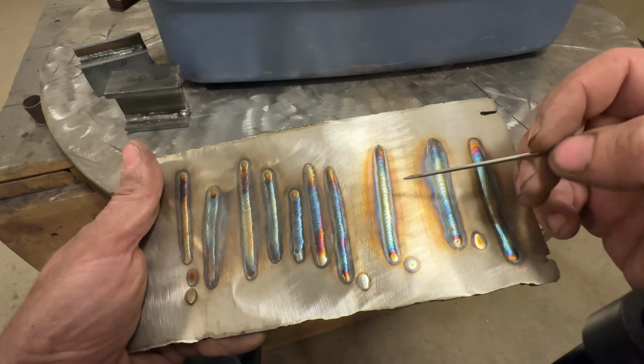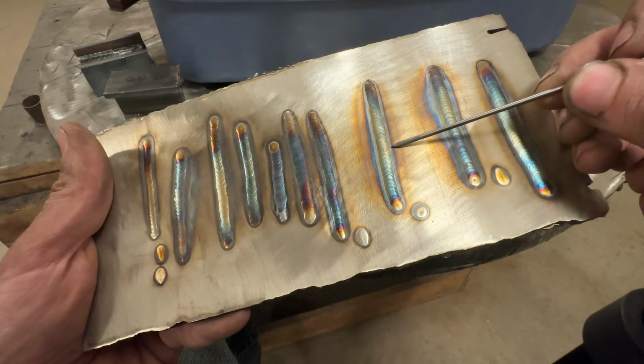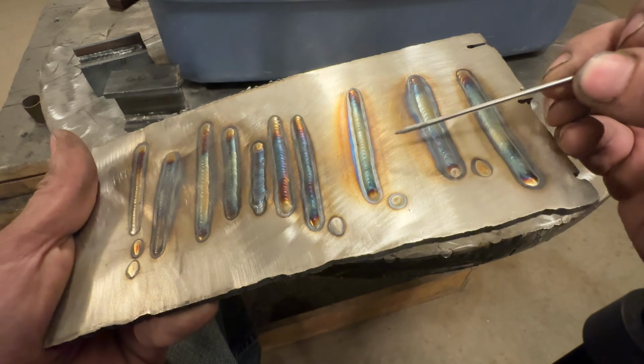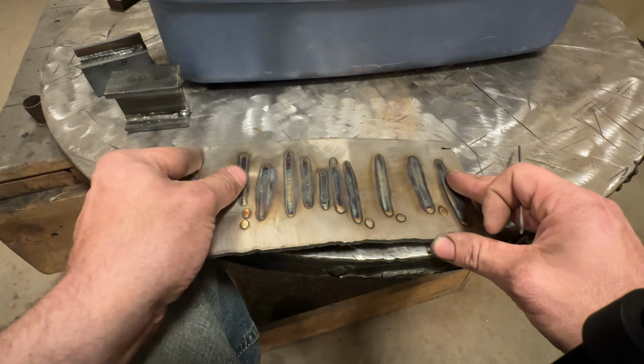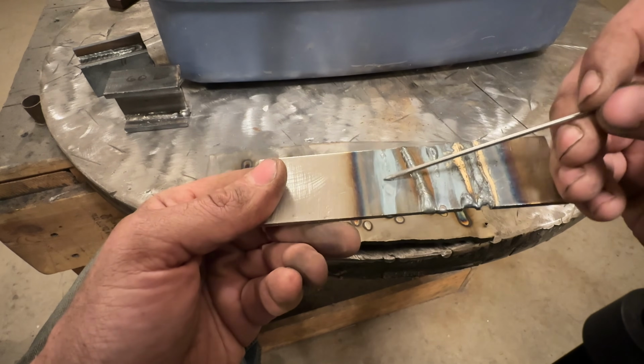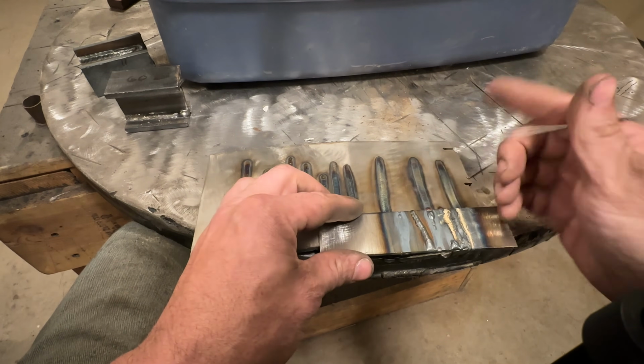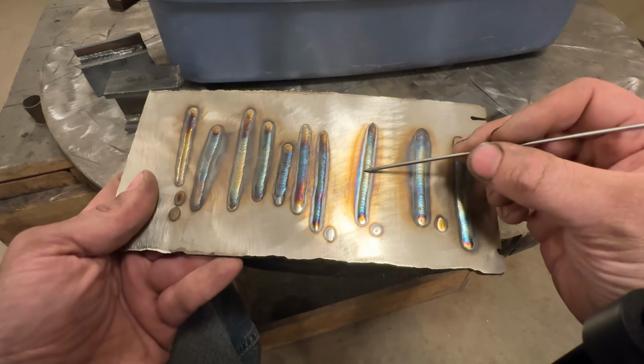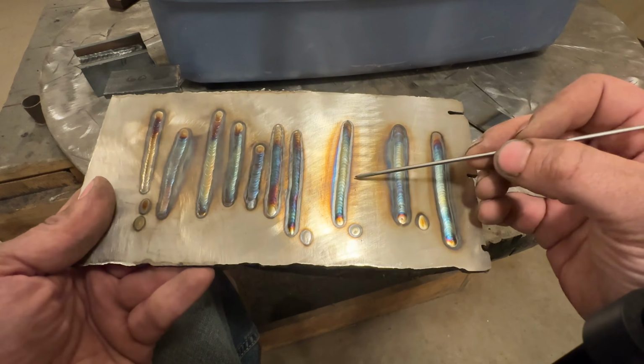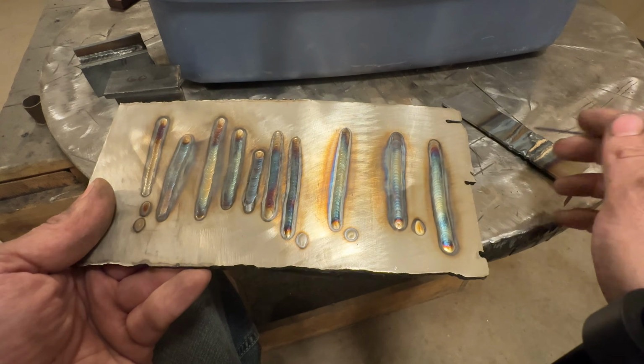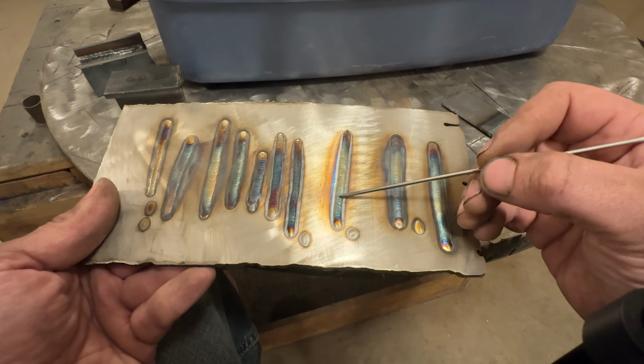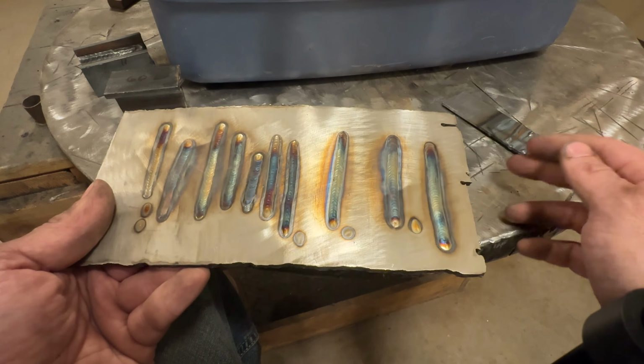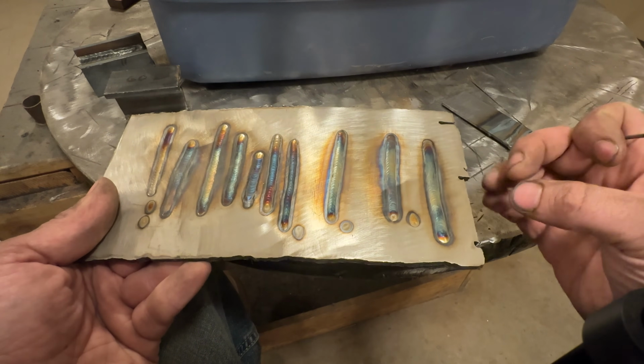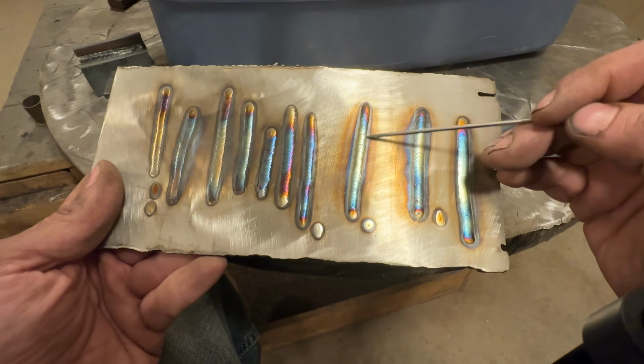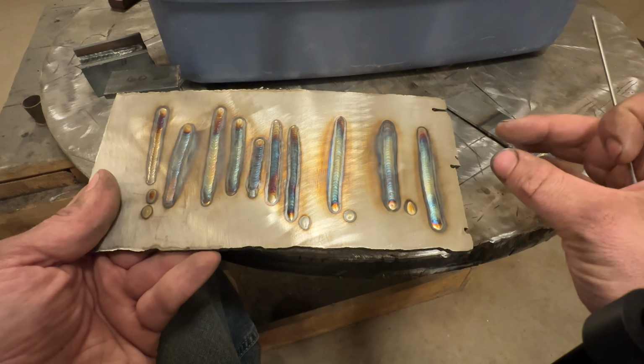The other interesting thing I'll mention before we move on is if you look here, you notice how this heat affected zone, the HAZ, is so close to the weld. And then when you look at clean steel, like this piece, you see how much further out it is. This color here on the side of the weld is the same thing as here. The difference is stainless steel is a very sluggish heat transfer material. It does not transfer heat very fast, and that's why it welds at lower amperage than steel does, because your weld pool gets hot and stays hotter because the heat's not dissipating through the material as much as steel. Whereas the opposite, aluminum, transmits it so well that you need a ton more heat. But that's essentially what you're seeing here, the same as this. It's just much closer to the weld.